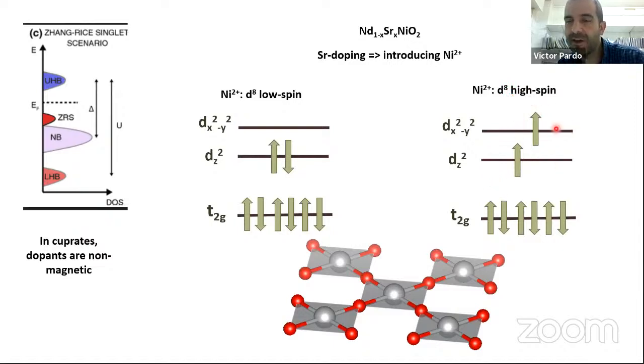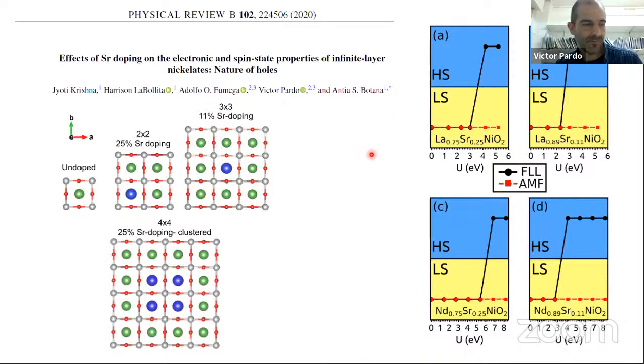That is very common in nickelates, but what about when you have square planar nickelates? Is it the same thing or is it different? And DFT calculations can actually answer this. So what we did was setting up supercells. We have the undoped case. We started with this 2x2 supercell, where one of the neodymiums is substituted by strontium here in blue. We did a 3x3 to mimic something closer to